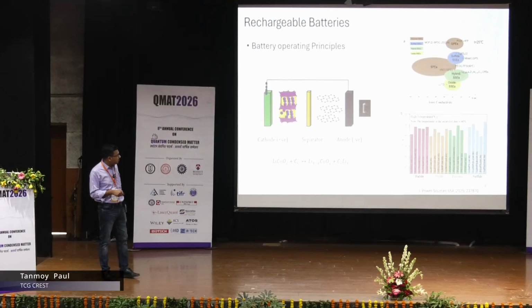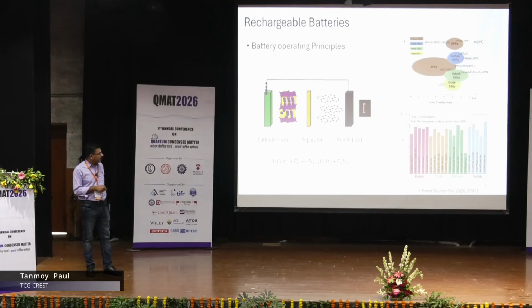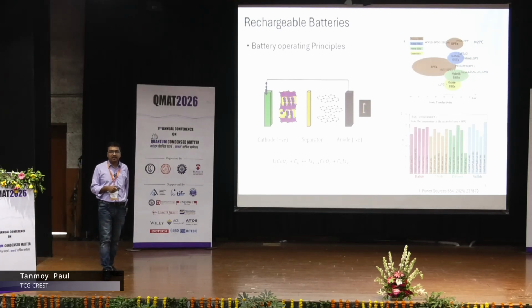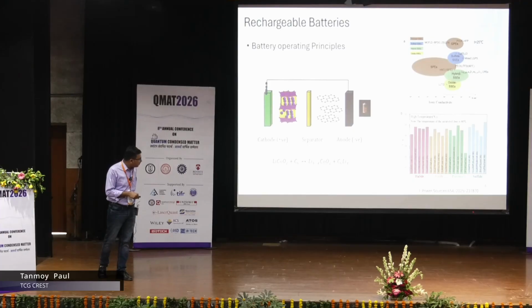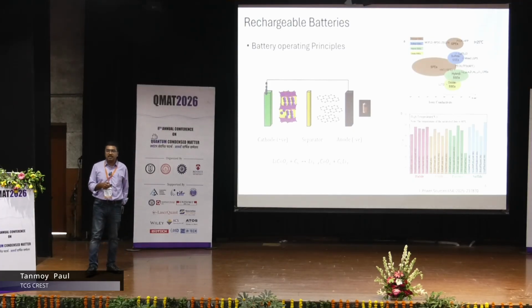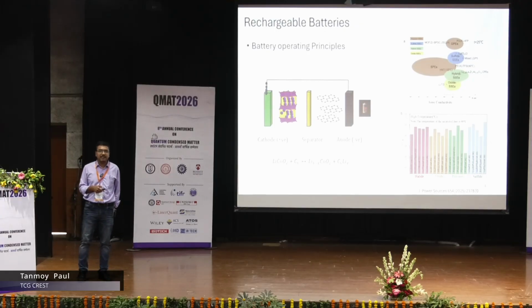For example, the halide solid electrolytes are mostly not very stable in static air, but the lithium indium chloride that we studied in this presentation is stable at room temperature and in normal air. Lithium yttrium chloride shows a better ionic conductivity than lithium indium chloride, but it is only stable in a flow of dry air.